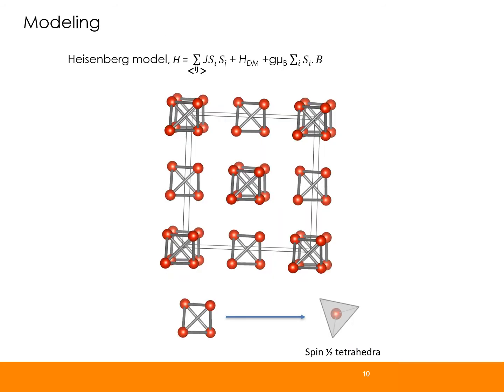Once we have the data, now we need to visualize the data. For visualization, we need a model. For the model, I use a simple Heisenberg spin Hamiltonian with the DM interaction and a g-tensor term. First, I didn't consider the DM interaction, but without adding the DM interaction, I couldn't reproduce the sloped feature of the spin wave along the 110 direction. So the DM interaction is mandatory at the temperature of 2 Kelvin.